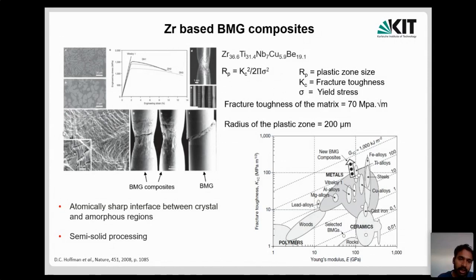So it is immediately obstructed by the crystalline dispersion. So that's what they have taken advantage of. This is one of the very few cases where they have shown tensile ductility. You can clearly see that they have shown necking in the sample, which is very, very rare in a metallic glass. So this is one of the very few experiments which was successful. And they have done that by semi-solid processing.